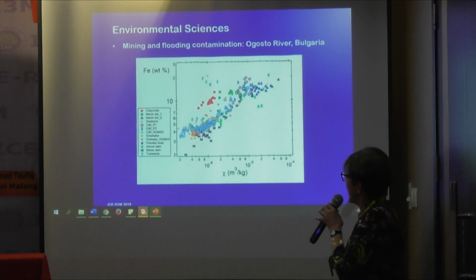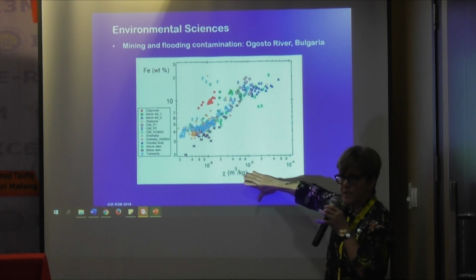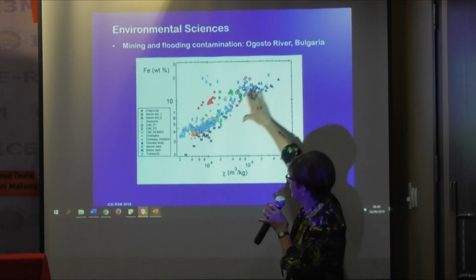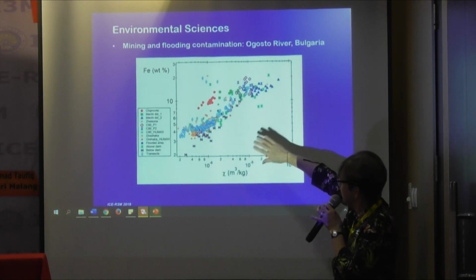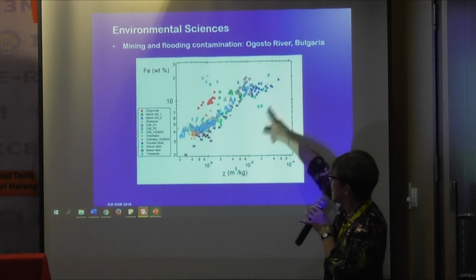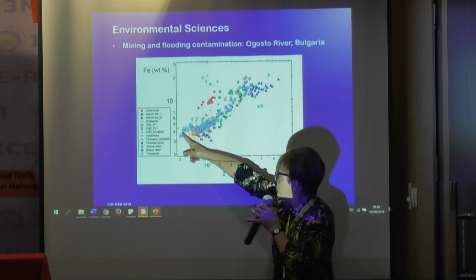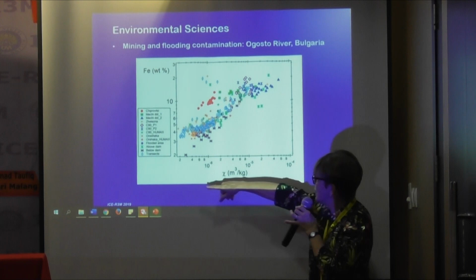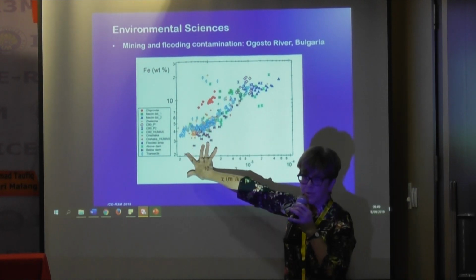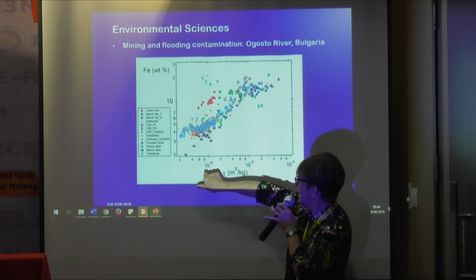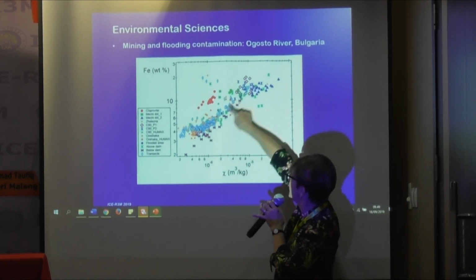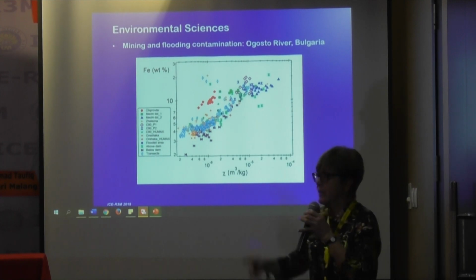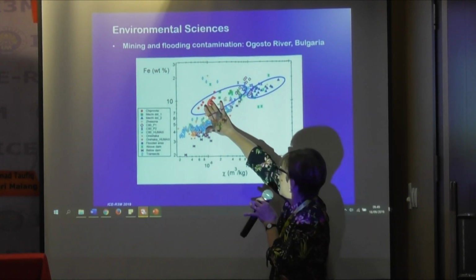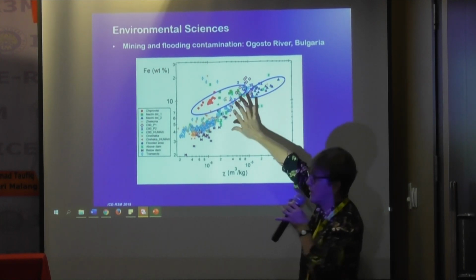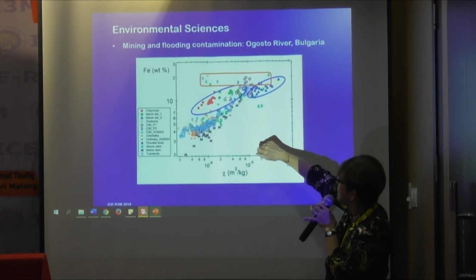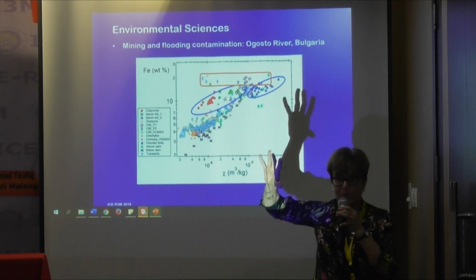Next. Okay, we looked at iron as a function of susceptibility in these soils. And you can see there's a very distributed distribution of susceptibilities going from very low to very high. It was very interesting. You saw iron would remain at 4 weight percent, but you would still get a pretty big range of susceptibilities. And it was only after you went up above about 1 times 10 to the minus 5 that you actually started to get a nice linear relation. Next. This is from the part directly where the tailing ponds had broken out. And next. And these are samples that are further away from the river.